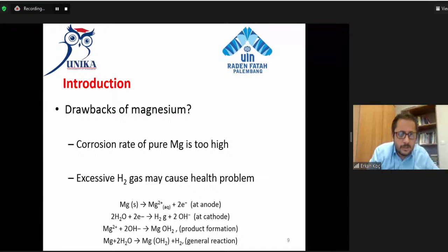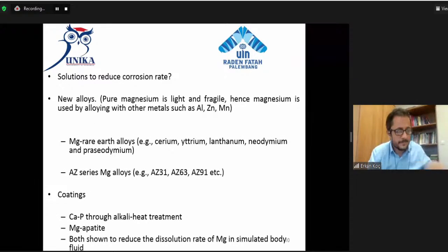What solutions are there to reduce the corrosion rate? This limitation can be improved by two methods: alloying and protective coating. We have to find new alloys. As I said before, pure magnesium is light and fragile. Hence, magnesium is used by alloying with other metals such as aluminium, zinc, and manganese. And also magnesium rare earth alloys.